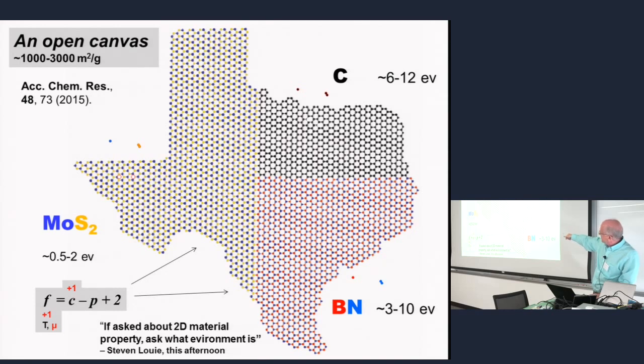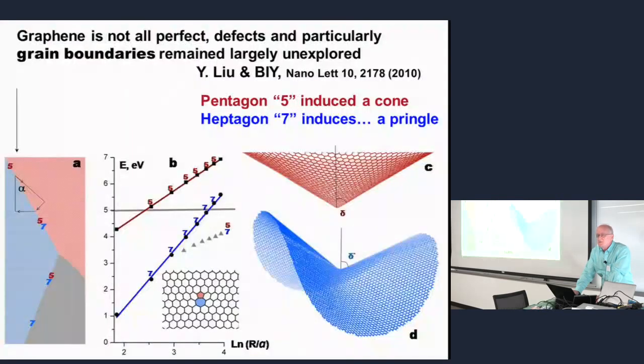Two elements, of course, also bring you a new degree of freedom, figuratively speaking, but also literally, because if you look at Gibbs' phase rule for degrees of freedom, it's number of components minus number of phases plus 2. So if you increase number of components, then it means that you add a degree of freedom. In this case, balance between elements can change composition easily. So this is a flexibility which we see in all defects and in lattices of 2D material. So we look at grain boundaries, we look at defects, and we try to learn what they are, and that's what I'm going to discuss. I'm not really watching time at all. 10 or 11 minutes. Okay, so I will just go quickly through basic things.